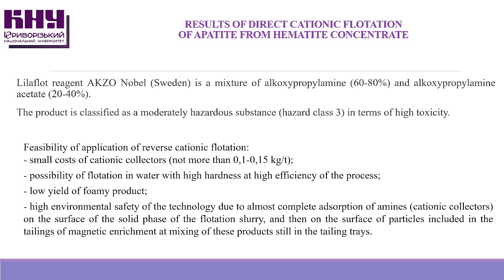According to its toxicity parameters, the product can be classified as a moderately dangerous substance of hazard class 3. Feasibility of using reverse cationic flotation: low consumption of cationic collectors, not more than 0.1 to 0.15 kg per ton; possibility of flotation in water with high hardness with high efficiency of the process; small output of foam product; high environmental safety of the technology due to the almost complete adsorption of amines, cationic collectors, on the surface of the solid phase of the flotation pulp, and then on the surface of the particles that make up the magnetic separation tails when mixed with other products in the tailings trays.